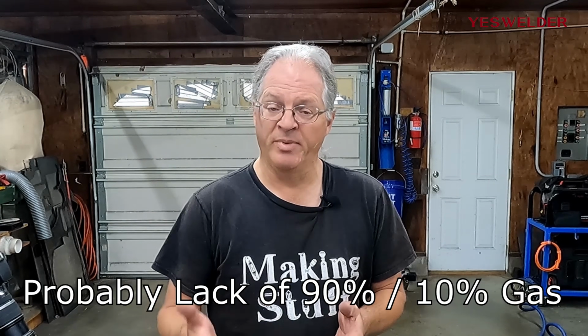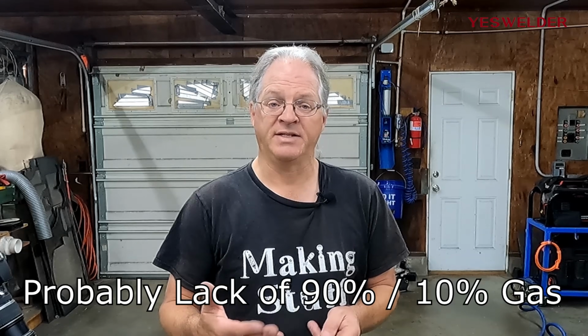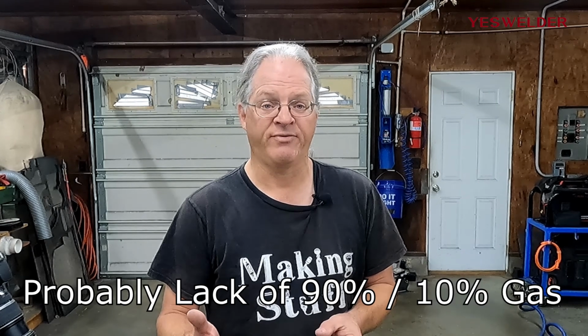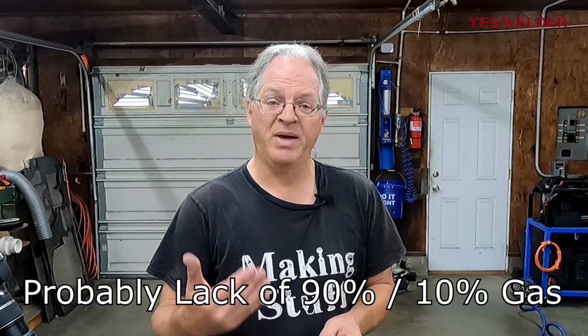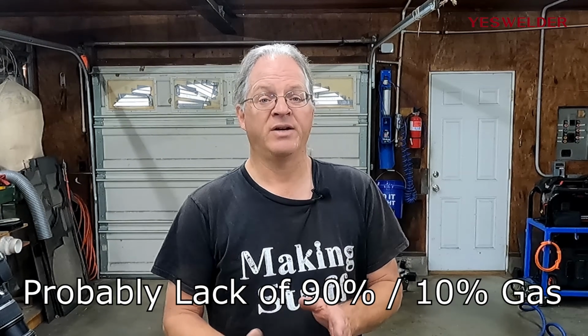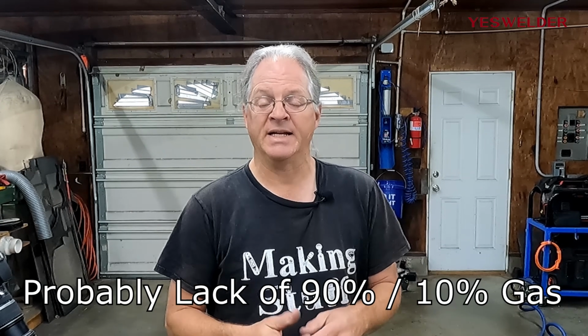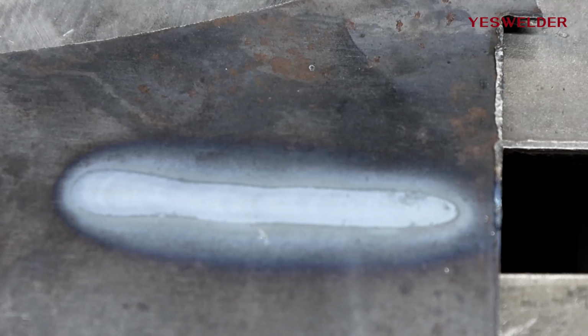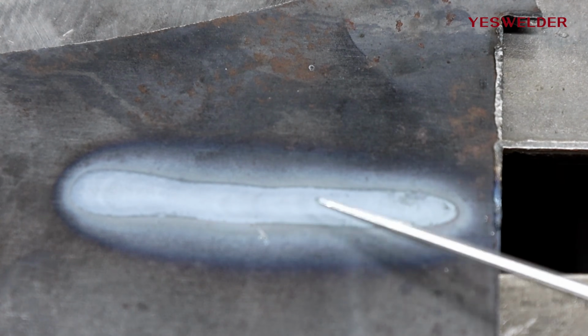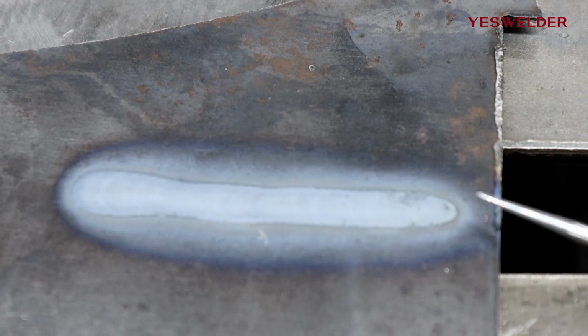I did get a little bit better result by increasing the CFM of the gas from 20 to 25. I also upped the peak current a little bit. Both of those seem to help, but like I said, it didn't completely get rid of the spatter. And if we flip it over and look on the bottom, you can see a heat line here, but nothing burned through.